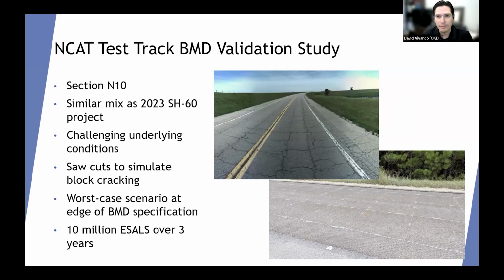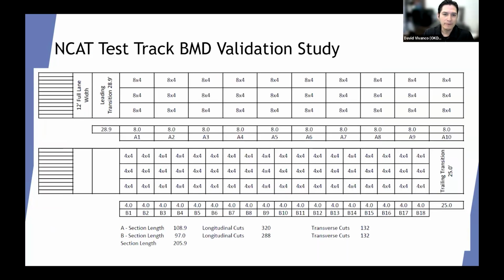So the idea is to put 10 million ESALs over 3 years on that section. I think so far it's been around 4 or 5 million ESALs, if I'm not mistaken. I think that mix started showing some cracking around the 3 million ESAL mark. So for us, that's actually a very successful mix, because that State Highway 60 project is a 3 million ESAL design life project. So it's showing us that we can go with that approach of requiring 100 on CT index, and we can use RAP up to 25% with a softer binder with acceptable performance. We saw cut that section, so we did sections of 8x4 feet and 4x4, to recreate that block cracking.